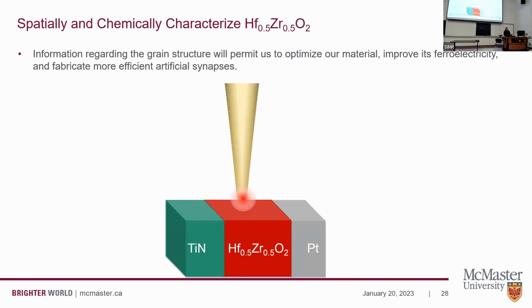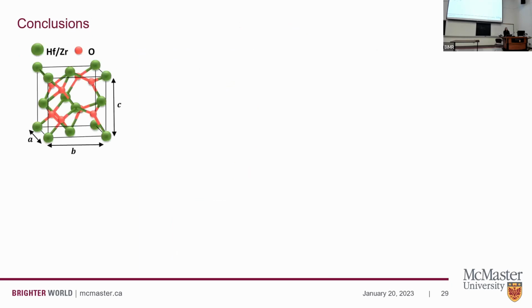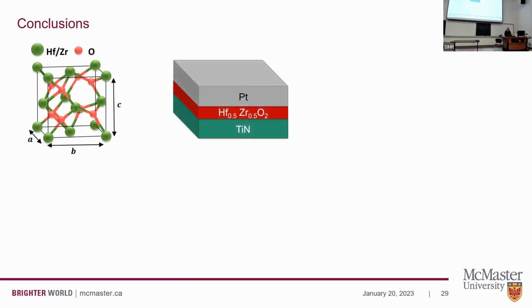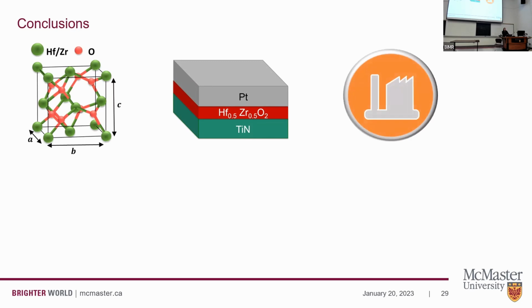Now, the next step would be, can we use this technique to image the grains in our hafnium zirconium oxide ferroelectric films? This is something that hasn't been done yet, and that would be a step forward. Getting this information regarding the grain structure would permit us to improve its ferroelectricity and fabricate more efficient artificial synapses. So in conclusion, we synthesized some ferroelectric hafnium zirconium oxide, and we used it to fabricate some ferroelectric tunnel junctions. And it's already identified for non-volatile memories because they are CMOS compatible, which makes them suitable for large-scale integration.